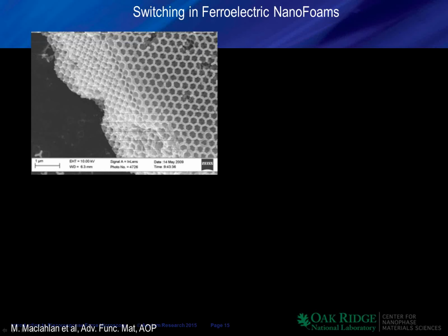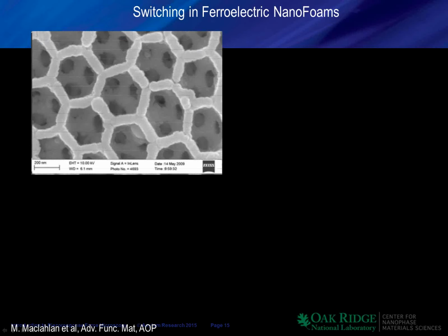Let's see what is the advantage of this approach. And the answer is that band excitation is optimal for studies of rough surfaces. This is an example of such behavior. This is a honeycomb structure made out of PZT nanowires. So if you will, this is as rough a surface as it can possibly be. If we look at it at higher resolution, you can see that these are really small wires arranged in this very friable structure. So let's try to do the BE SS-PFM, or BEPS, measurements over the structure.